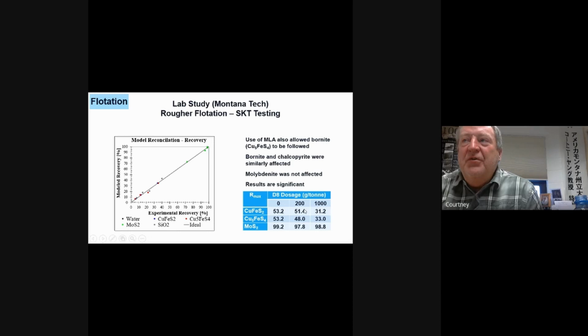And then as you increase the D8 dosage, the recovery went down a little bit. Now, mind you, we're not really high here. Then we put it up to 1,000, and then this came down even more. And if we were to go up around 1,300, I wish we had done those tests, but we didn't. We would see these numbers come down even more. Another point is that the recovery really doesn't change for the moly. So the chalcopyrite and the bornite start to get depressed, and we're able to follow the bornite because of the use of the MLA.